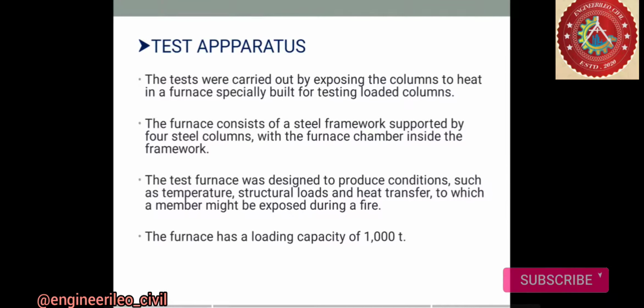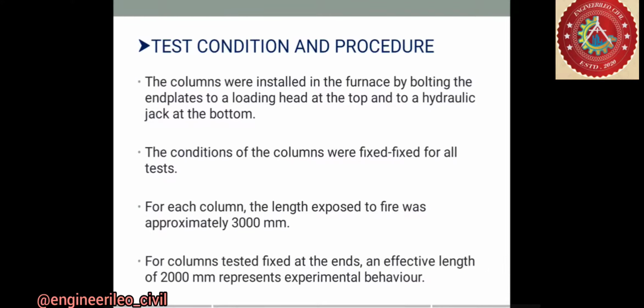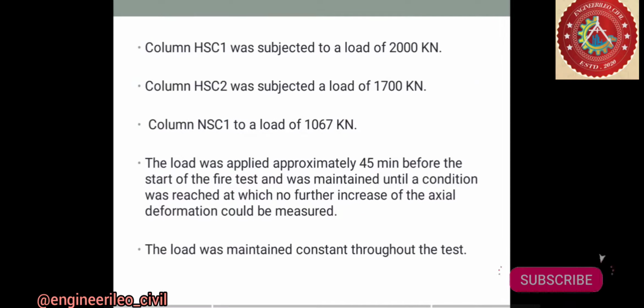You can go through that written part. The columns are installed and the end plates of the furnace are installed by bolting at the loading head and the hydraulic jack at the bottom. Then the columns are fixed, with fixed end conditions. For each column the length exposed to fire is approximately 3000 mm, and the effective length is 2000 mm. For high strength concrete columns, the first is subjected to 2000 kilonewton load, the second to 1700 kilonewton load, and the third to 1067 kilonewton load. The load was maintained constant throughout the test.